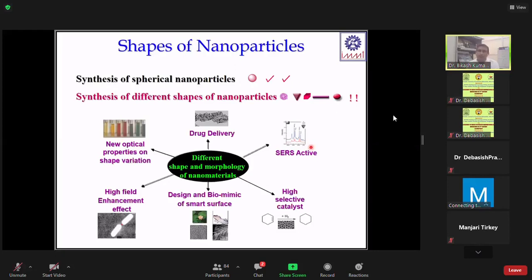You can see that the optical property of the nanoparticle changes when you tune its shape from spherical to different kinds of shapes like prisms, spherules, rod shape, cube shape, or other shapes. Usually the spherical nanoparticle has one color, but you can get a different color of nanoparticle by only tuning the shape. The rod shape gold nanoparticle will have a different color, and the optical behavior will be different. In the UV-visible spectra, you will get two absorption bands, one longitudinal and one transverse. But in the case of spherical, we will get only one band.